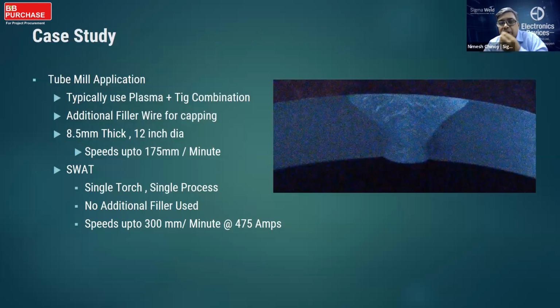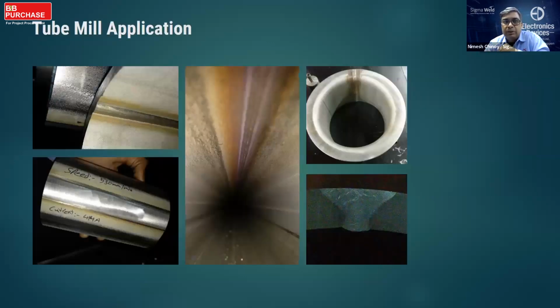For the tube mill application, we were able to do for our client, increase the speeds for an 8.5 thick pipe, 12-inch dia, from 175 millimeters a minute to 300 millimeters a minute. And with this, you were able to avoid the filler wire altogether and yet get the RT joints 100% of the time. These are a few of the photos of the joints concluded.